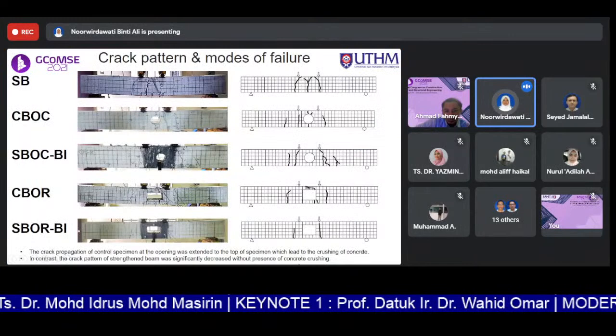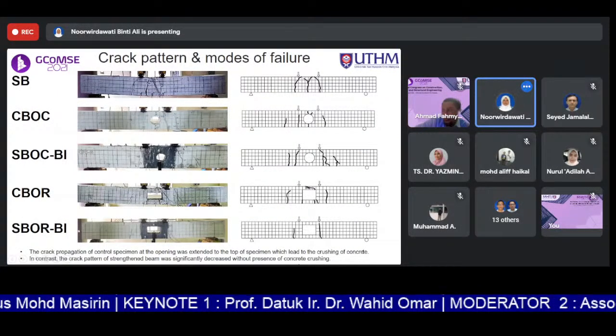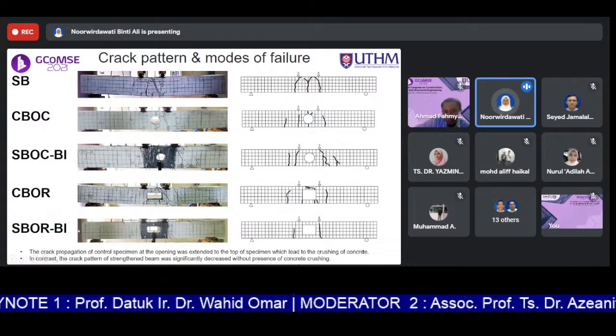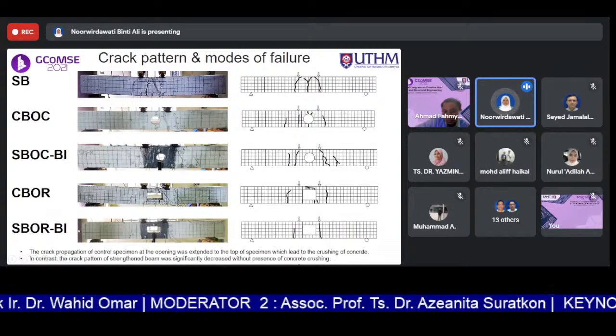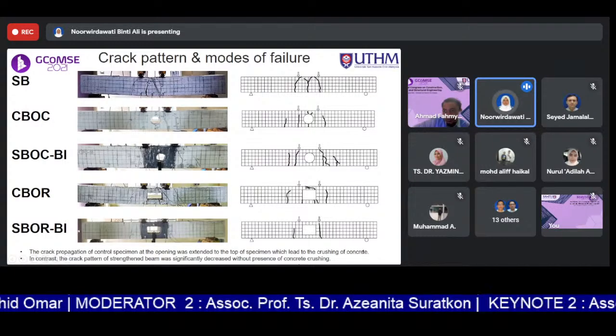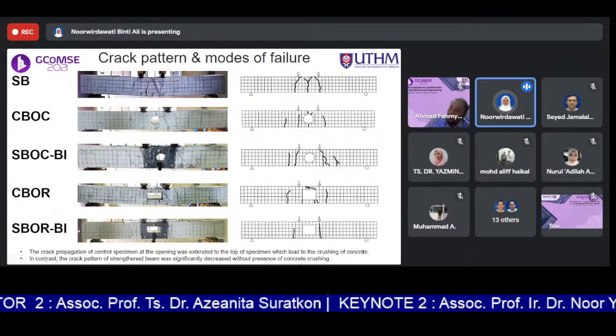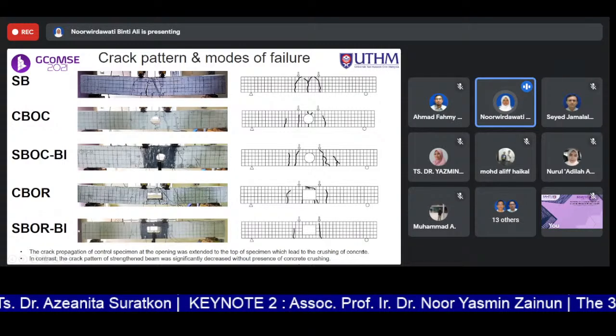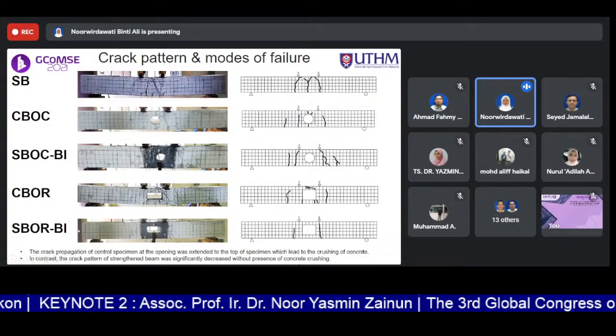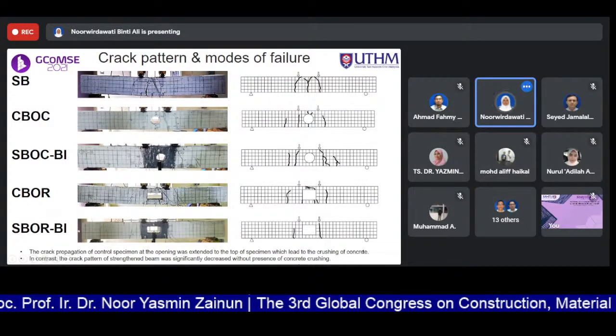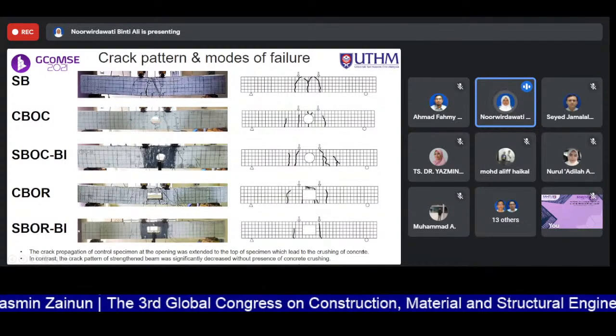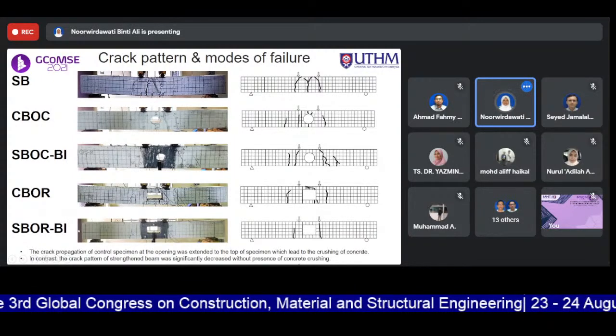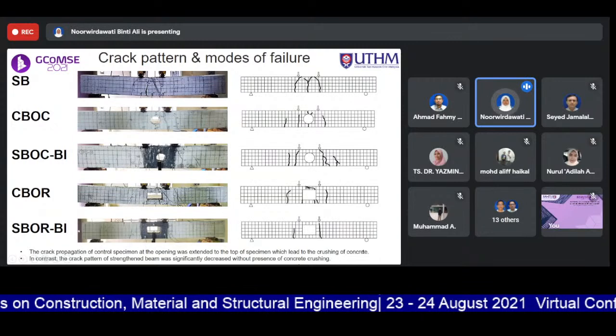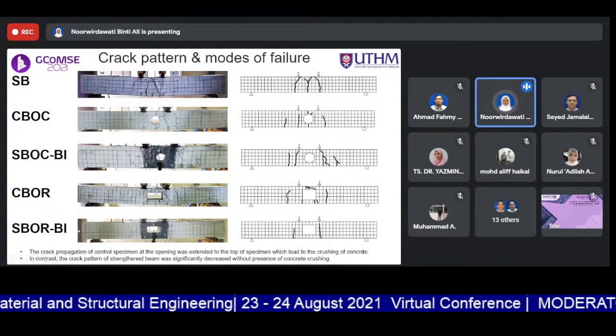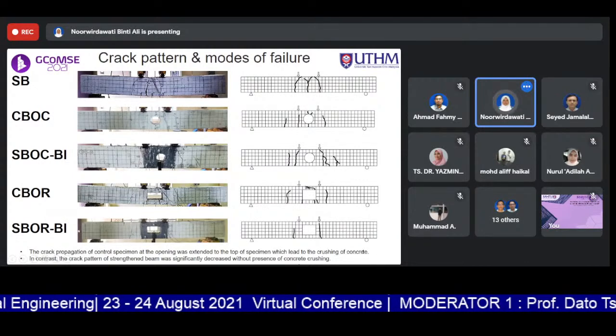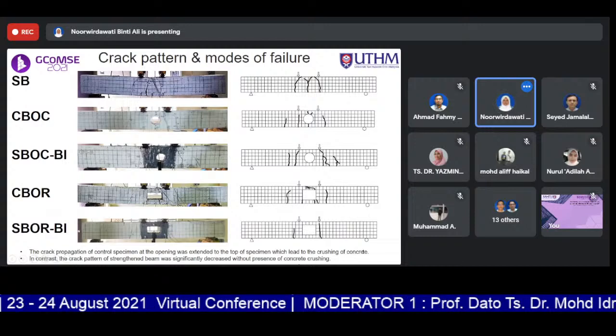And these are the crack patterns and mode of failure of all beams. Basically, the crack propagation for all specimens is almost similar, where all cracks at the beginning of the loading started at the soffit of the beam, and then go to the point load location. The difference is for the strengthened beam, of course, we cannot see clearly the crack propagation at the CFRP area because there is CFRP there. So we cannot observe what happened inside or at the face of the concrete.